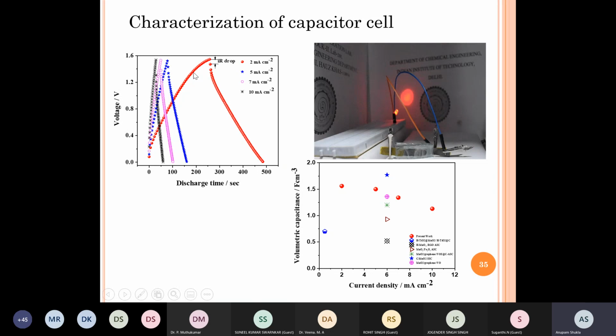This is the same characterization for a symmetric capacitor made out of those electrodes. So we took two of such electrodes, combined them together, and put sodium sulfate as an electrolyte, so an aqueous solution, and this is the curve that you get. Now in this curve, for a capacitor, because now there is still a thicker volume of electrolyte, you will start seeing the IR drop that we were talking about. So resistance, ESR, becomes a noticeable component here.